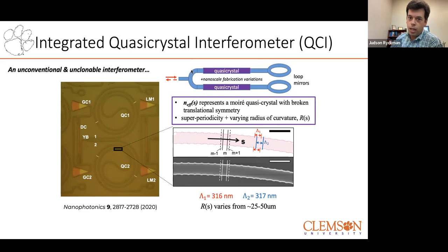So here's a loop mirror that just reflects the light back, and another one to reflect back. But instead of a conventional Michelson interferometer, which would certainly be clonable, we insert these quasi-crystals, which are basically small corrugations on the waveguide using this Moiré pattern, and also the fact the spiral has a varying radius of curvature. This quasi-crystal breaks the translational symmetry, and it essentially introduces a very high sensitivity to nanoscale perturbations. And you can even visualize some of these, this is manufactured imperfectly. There's sidewall roughness, there's nanoscale errors in the width, and we're going to harvest those errors such that any two devices we fabricate, despite having the exact same design, will give completely different output behaviors, and that makes each one unclonable.